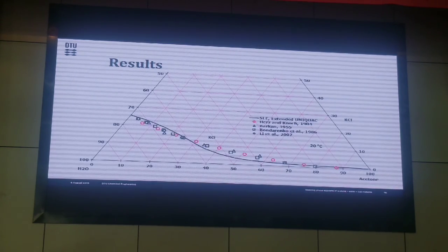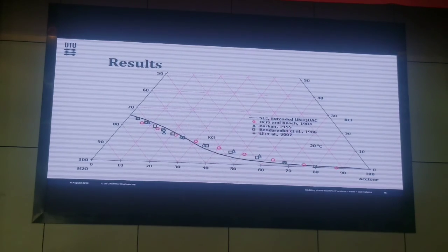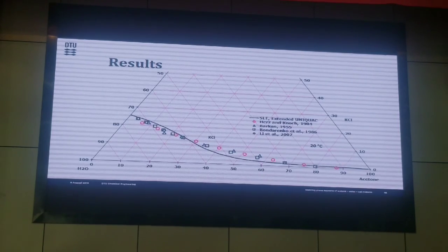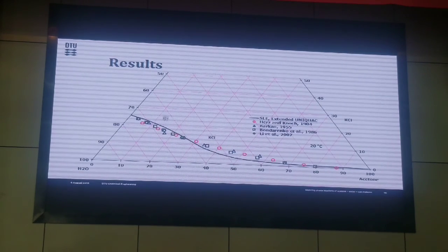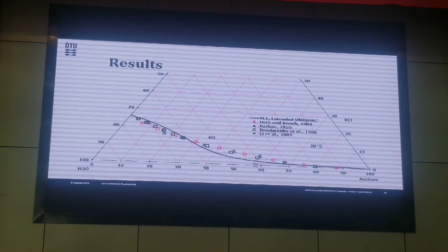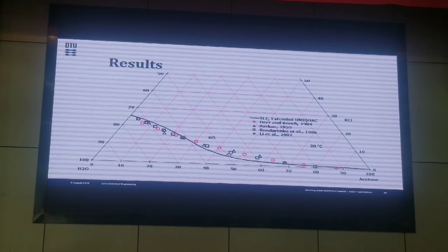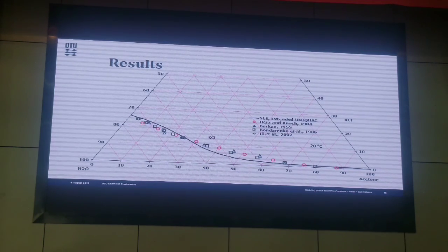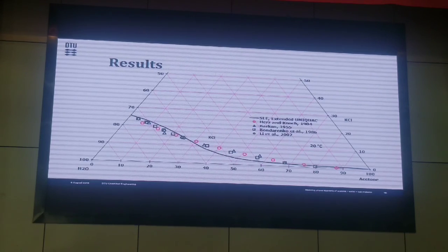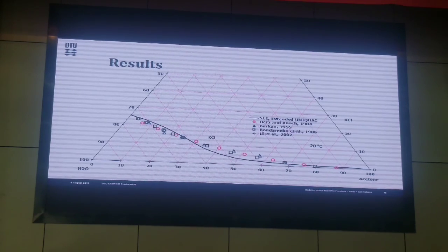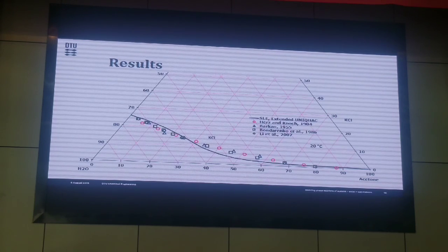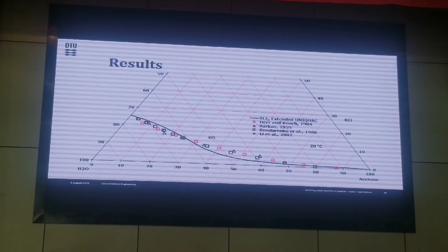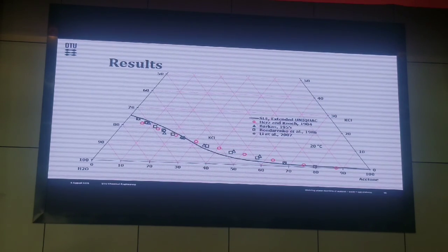And here's the data of potassium chloride at 20 degrees C. This is all solid equilibrium data. And the curve is a little bit funny, going down below here. This was the system where there should only be liquid-liquid equilibrium at temperatures above 32, but according to the model, it starts already at 22. But there is no liquid-liquid equilibrium at 20 degrees, which is good, because according to experimental data, it's only solid.